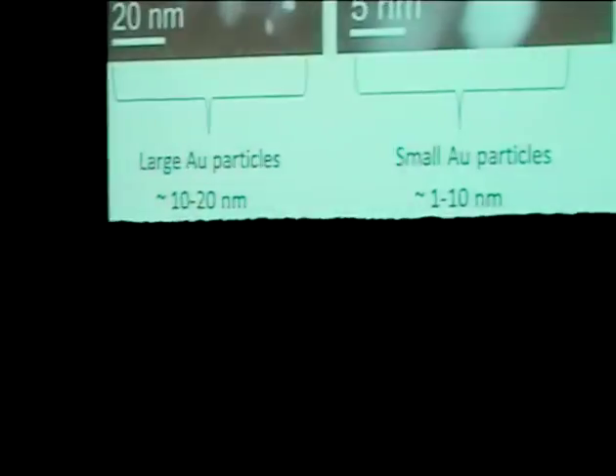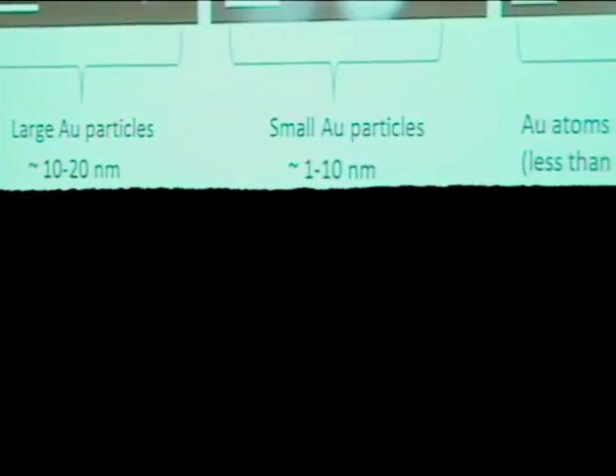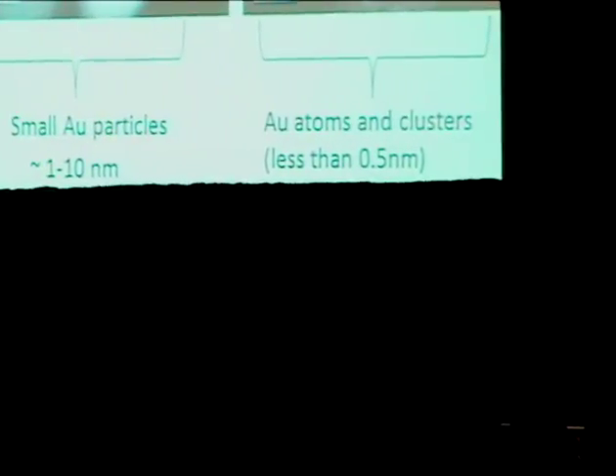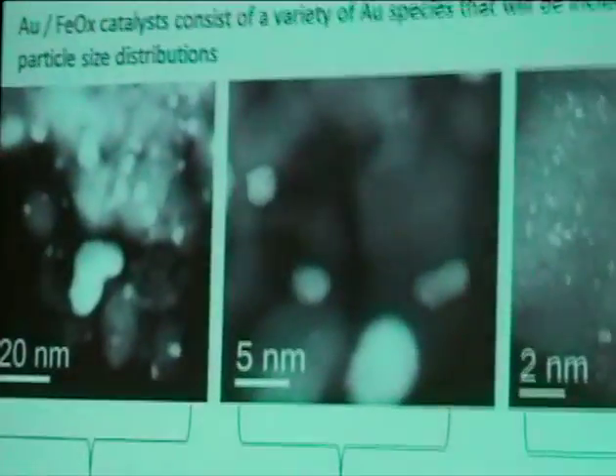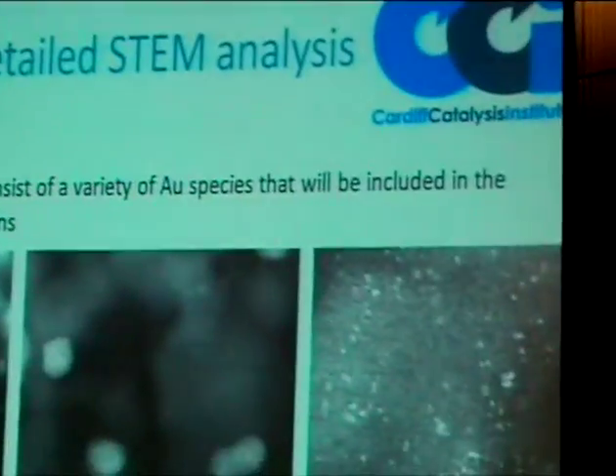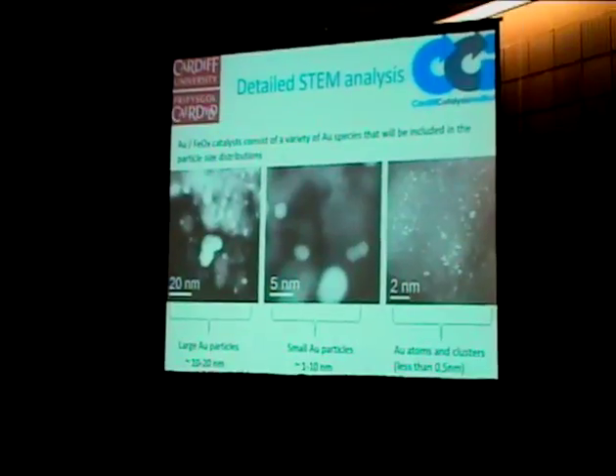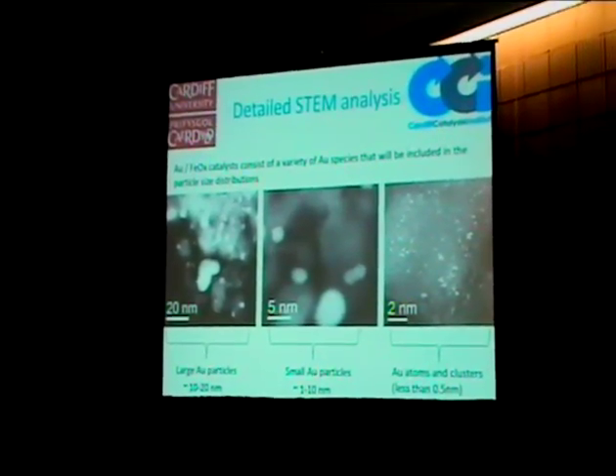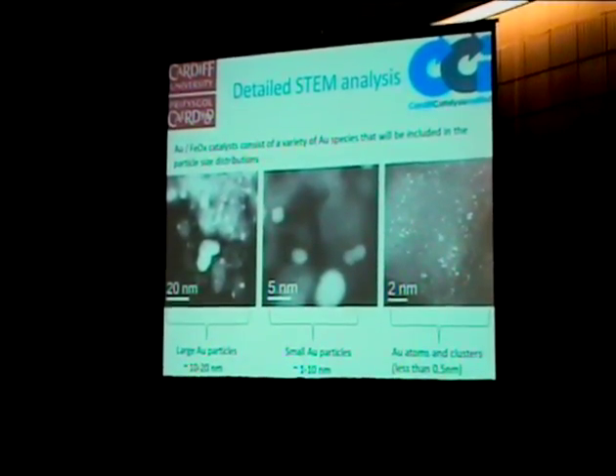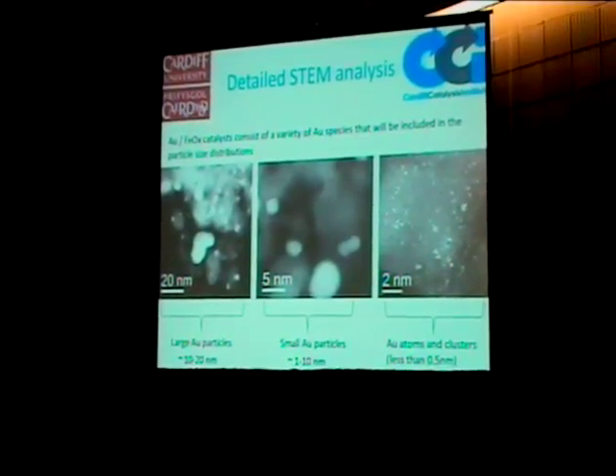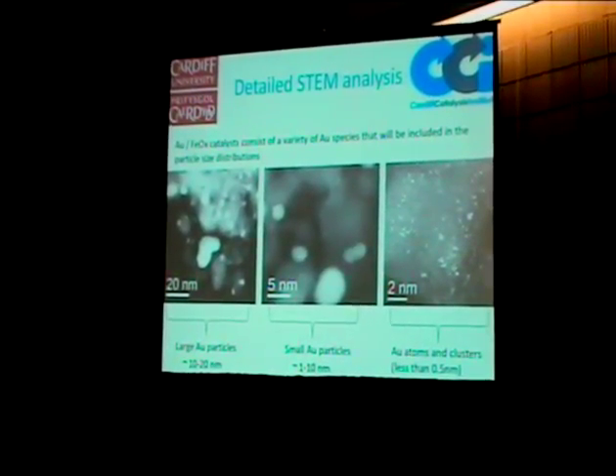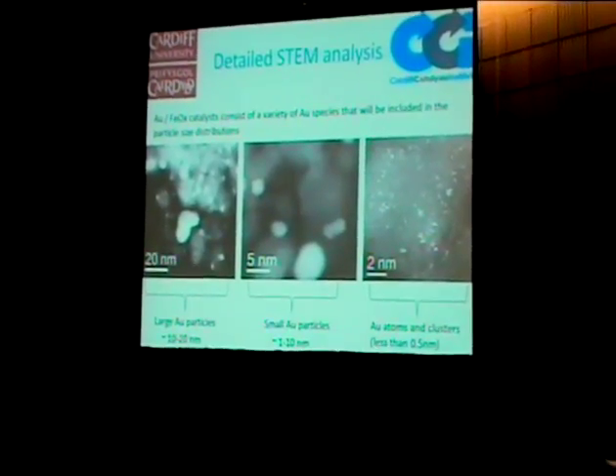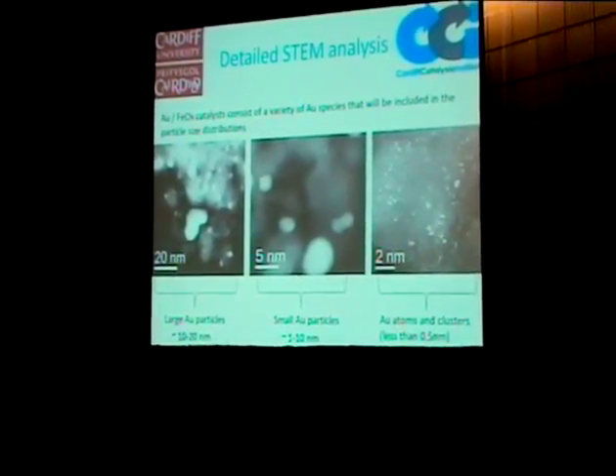On closer inspection, these catalysts were shown to contain a number of gold species. So, large gold nanoparticles, around 10 to 20 nanometers in size, assumed to be not contributing too much to the catalysis. It was shown to contain small gold nanoparticles around 1 to 10 nanometers in size, as originally shown by Professor Haruta. And we could also image isolated gold atoms and small gold clusters smaller than a nanometer, and these could also be split into monolayer and bilayer gold structures.